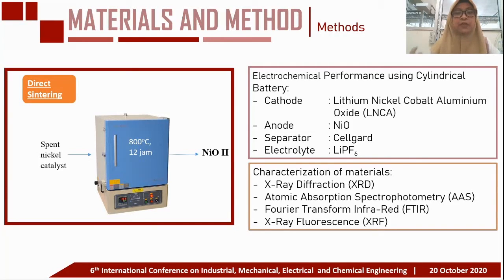The crystal structure was investigated by XRD. Metal ion concentration was analyzed by AAS. Organic and inorganic materials were identified by FTIR, and elemental composition was investigated by XRF.